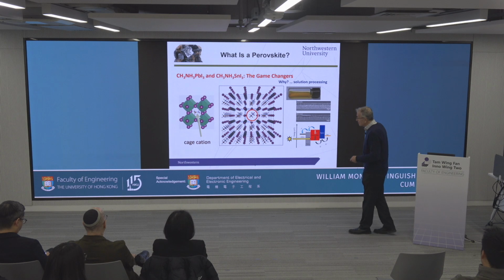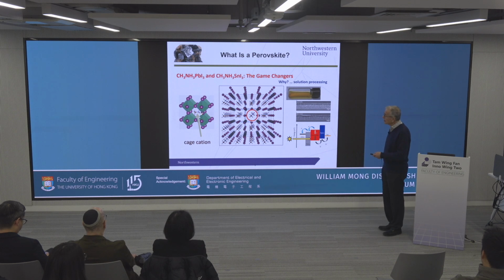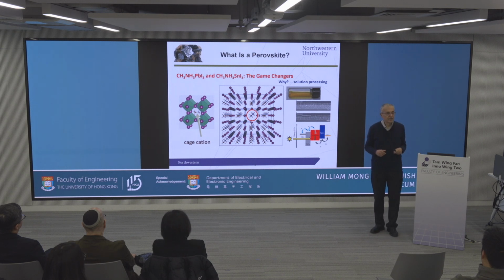And this is the crystal structure. Well-known crystal structure is known from the oxides, and these are the halides, however. So the structure itself is an octahedron of metal surrounded by 6 ligands, which are then the octahedra share corners, and that creates a 3-dimensional structure, and it has a small void.